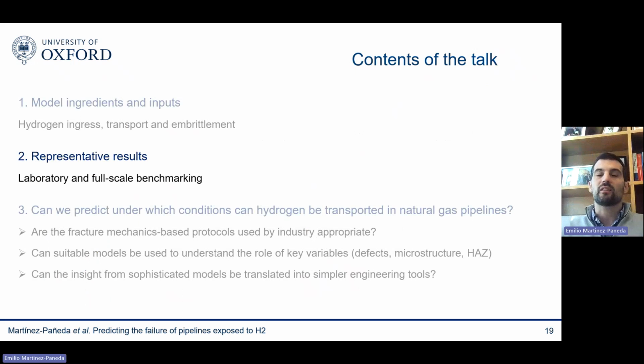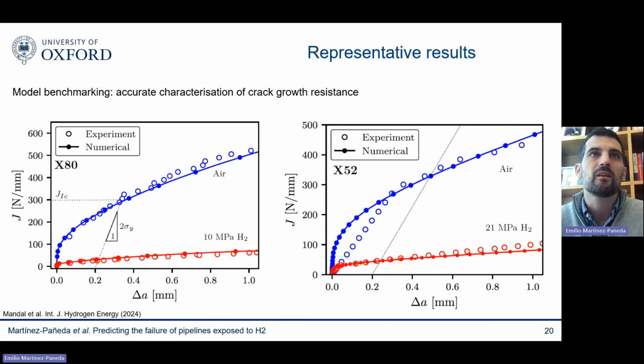So let me show you then some representative results showing how those models can blindly predict the outcome of experiments. And then we will focus on our problem at hand, the pipeline problem. So you can see here a comparison with two pipeline steels. These are our crack growth resistance curves. So these are the outcome of fracture experiments in air and in hydrogen. You can see this is an X80 and an X52 steel. And you can see that we get a very good agreement in terms of the J versus crack extension in both cases, for both materials.